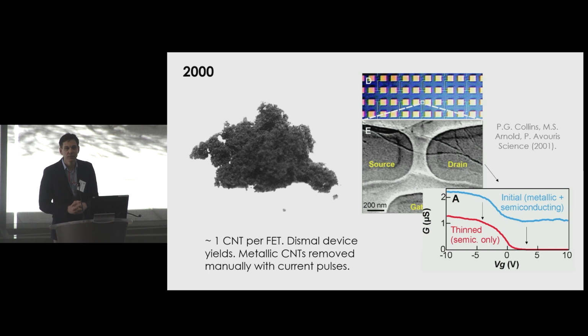Back in 2000, when I started working on nanotubes, here's what we did. We took this powder, we put it in a solvent, we ultrasonicated, which broke apart all the tangles of trillions and trillions of nanotubes in that powder. They were floating around, and we would just spin coat them onto a wafer. We would then put down electrodes for source and drain and use the backgate. And occasionally, a nanotube would cross between our electrodes, and we'd have horrible device yields. There'd be maybe one nanotube or bundle of nanotubes per transistor.